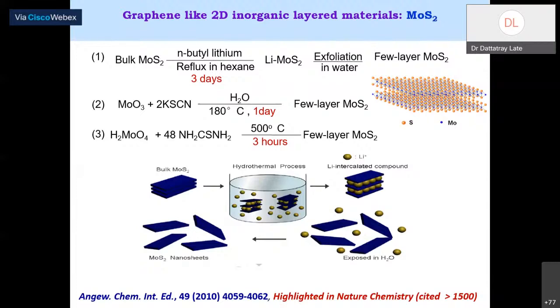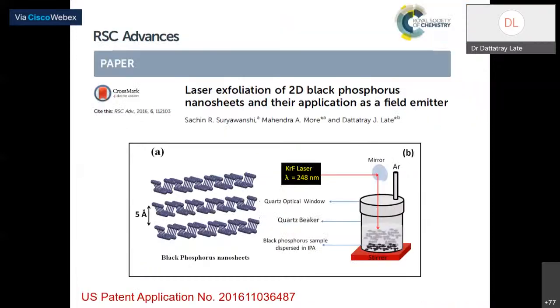So we heat these again, similarly at 500 degrees Celsius in a furnace for 3 hours, and you have a few layers of MoS2. Basically, you can see the schematic of how exfoliation happens in water. Your bulk MoS2 goes through the hydrothermal process, so lithium goes in between these layers, forming a lithium-intercalated compound. And when you do a simple exfoliation in water, you will be able to separate out these MoS2 nanosheets, right?